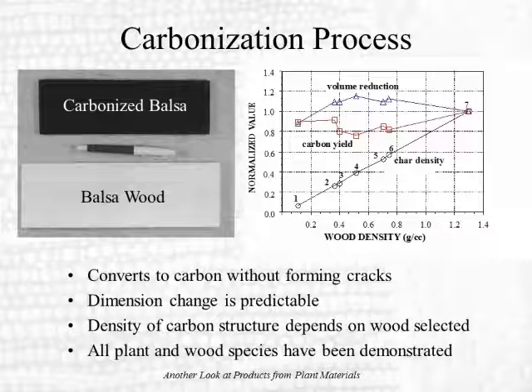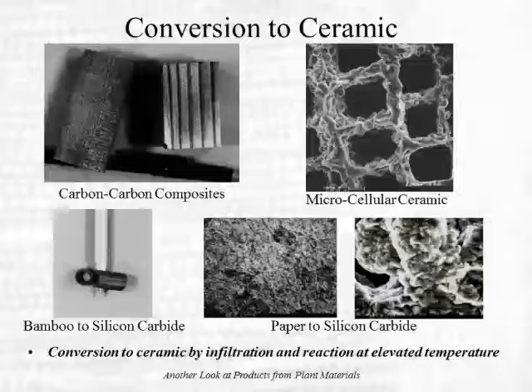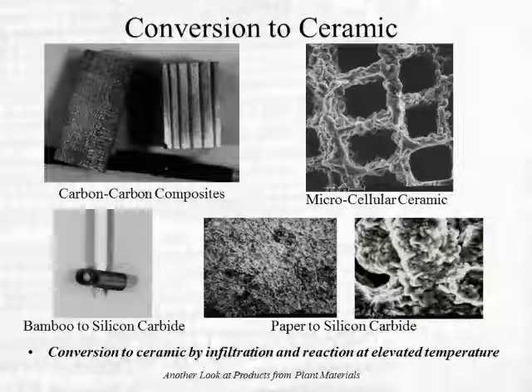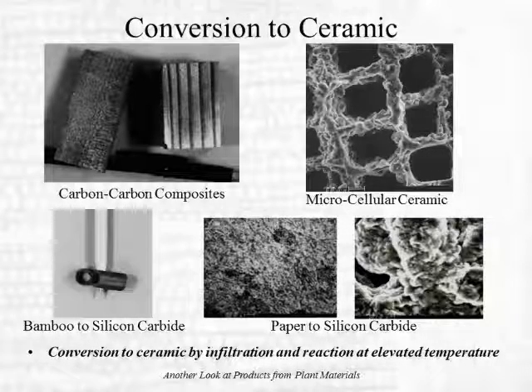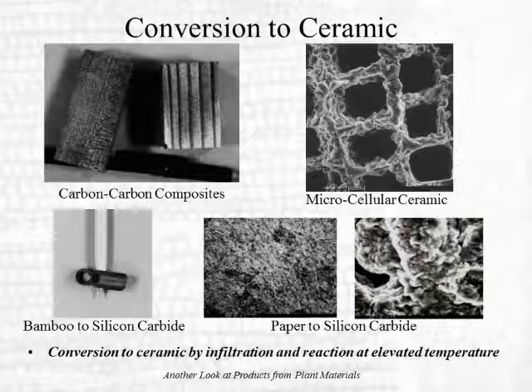So what this tells me is that, first of all, if you do the pyrolysis step right, you can make charcoal without forming cracks. It has structural integrity. The dimensional changes are predictable. The density of the carbon structure is going to be something you can select based on the precursor wood. And we've gone through and done all these different wood species and other plant species as well.